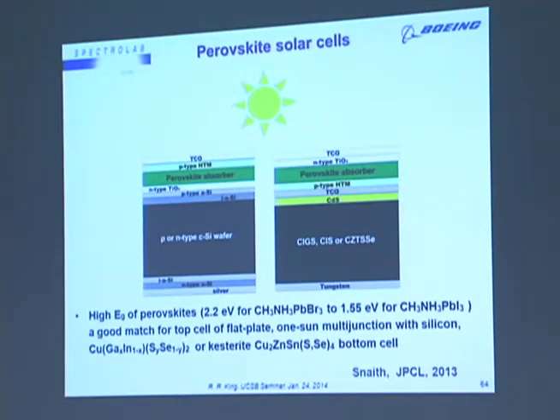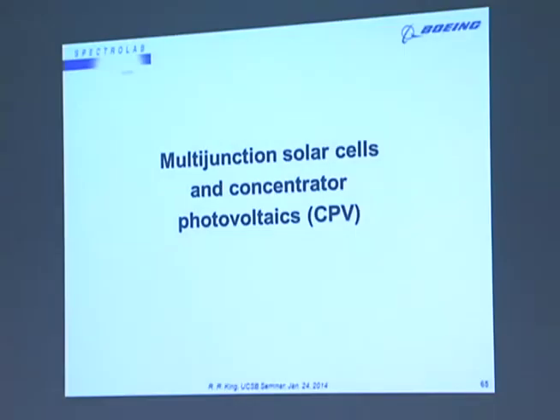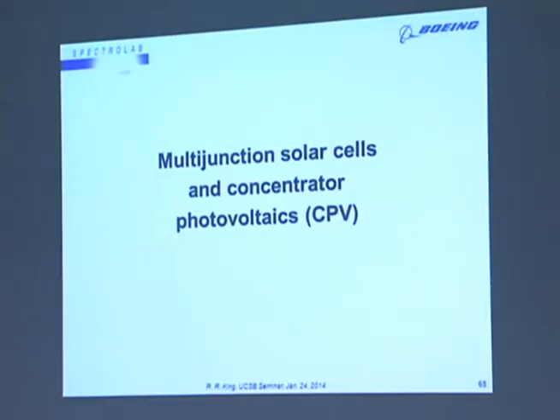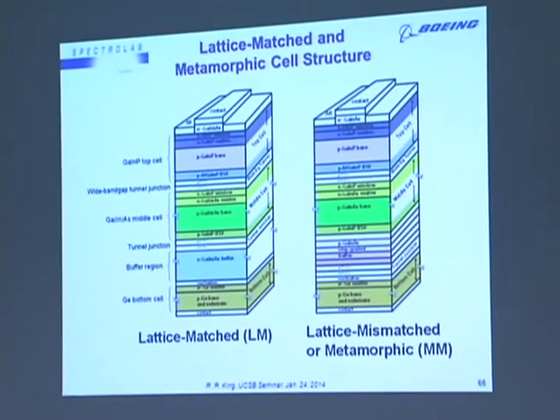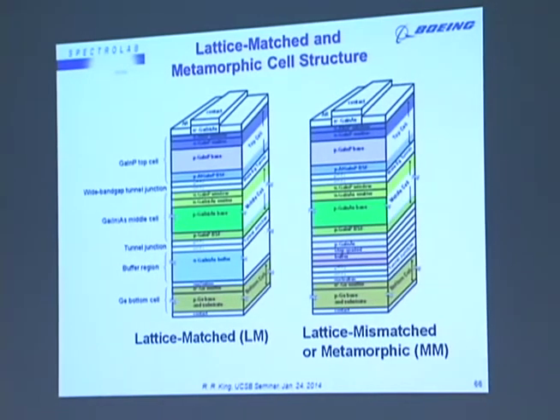But one very appealing thing about them is that the perovskite absorber has a fairly high band gap, so it can be placed on top of, for instance, a copper indium diselenide low band gap material to form multi-junction one-sun cells, which would potentially have much higher efficiency than today's single-junction silicon cells. So I wanted to get to the point where we can talk a little bit about multi-junction cells.